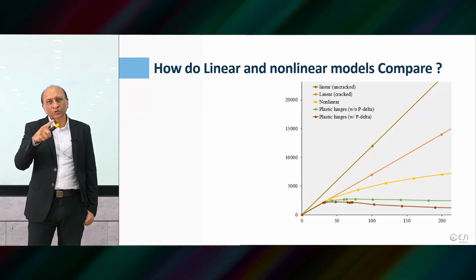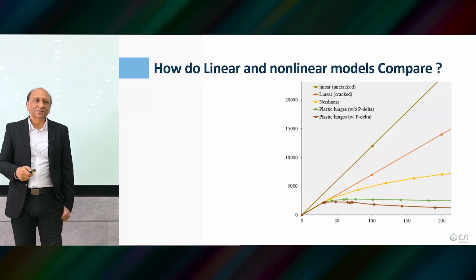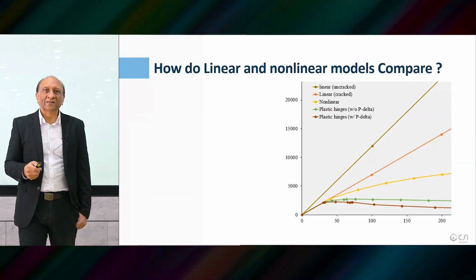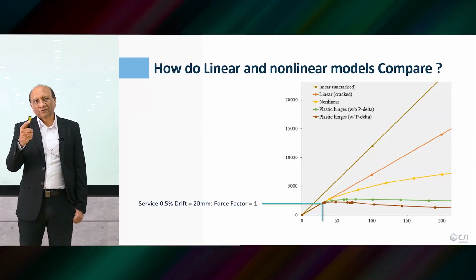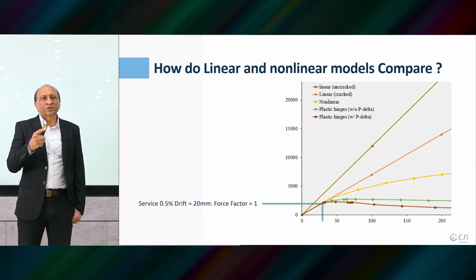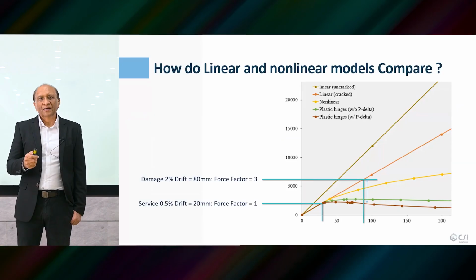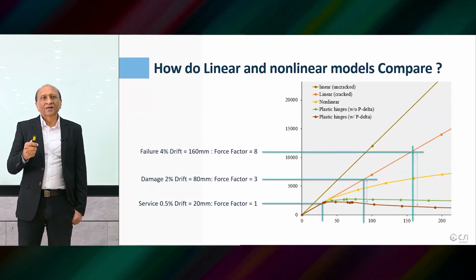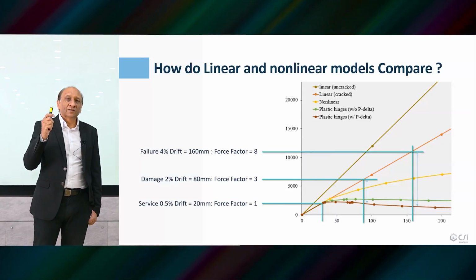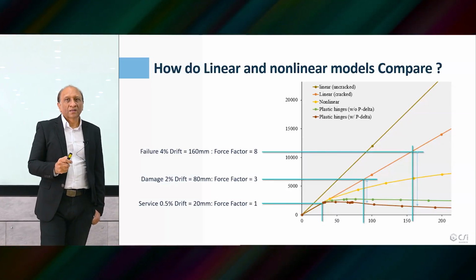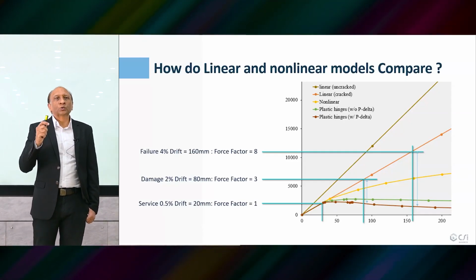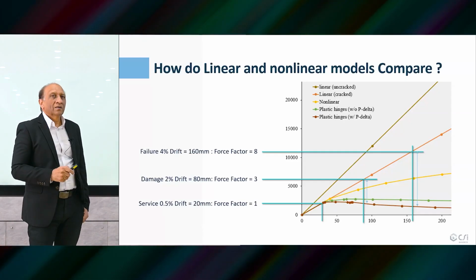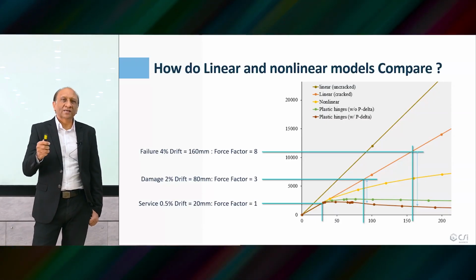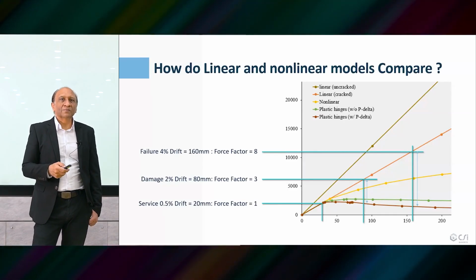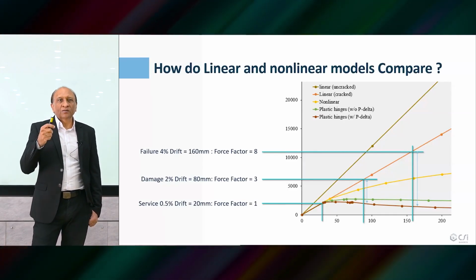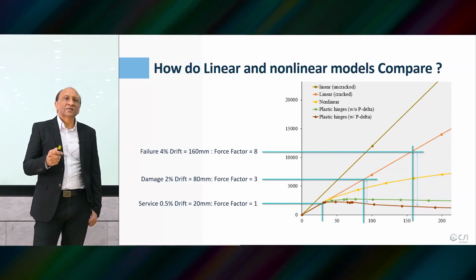can see that the curve starts to keep dropping, and you get much less capacity for force for a same displacement. And you can see here, for example, for this one, 0.5% drift, you get 20 millimeter, force factor, let's say 1. This one, 2% drift, force factor 3. 4% drift, force factor 8. That means the force is reduced by 8 times by using nonlinear analysis compared to a linear analysis using the code cracked section analysis. That's it. Well, just one case. Of course, it can vary. I'm just giving you a simple sample case, but just an idea that nonlinear analysis reduces the force capacity so much.